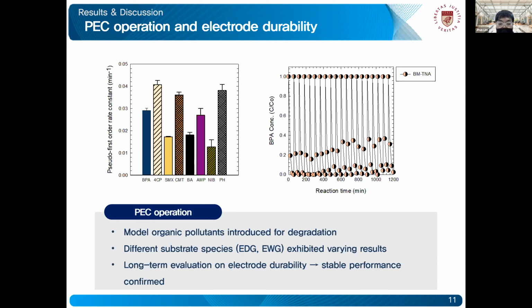Moving on, we evaluated the long-term durability of the electrodes through long-term operation. The evaluation was conducted for approximately 20 hours. As you can see from the figure presented on the right, stable performance was confirmed throughout the 20-hour analysis.